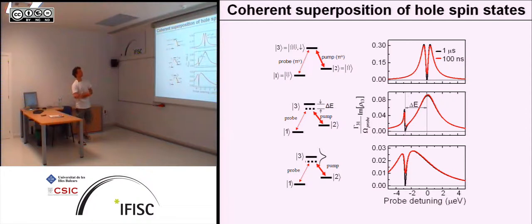To compare it to some theory, this is this classical lambda system and the graph I've shown before. So if you now look at a 1 microsecond coherence time of the ground state, you see this interference, or this dip goes all the way down to 0 because it's very long-lived, and you don't need to initialize it so often. So once you initialize it, you will sit here for a very long time. But if you decrease this to 100 nanoseconds, this dip moves up, and it will move up more and more the less coherent the system gets. So that is how you measure the coherence time of these two ground states.